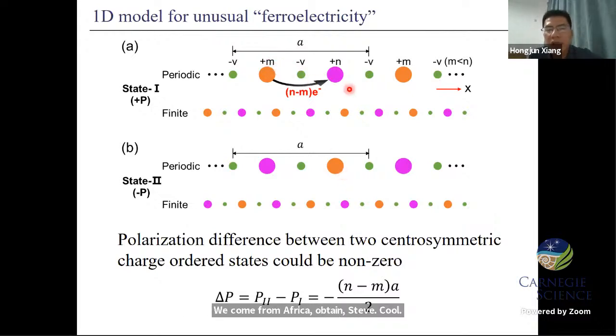So this kind of charge transfer will give rise to the polarization difference. So it will be non-zero. This suggests that the polarization difference between the two centrosymmetric charge order states could be non-zero. This means that maybe an electric field can induce the transition between the two centrosymmetric states.